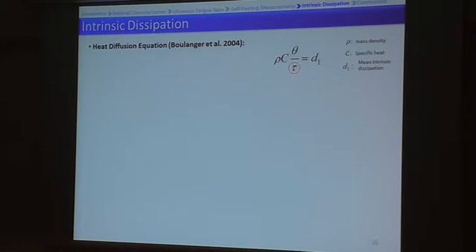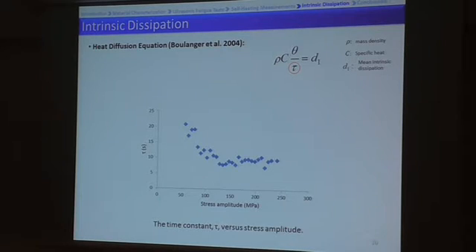And in order to measure tau, we use the slope of the self-heating diagram, the temperature evolution diagrams, just after stopping the test. And we obtained this diagram for changes of tau for different stress amplitudes. So as you can see, tau decreases by increasing the stress amplitude, and finally it reaches nearly a steady state. Therefore we can use the value of tau for each stress amplitude, and just by using this equation we know theta also, so we can measure the dissipated energy for each stress amplitude.